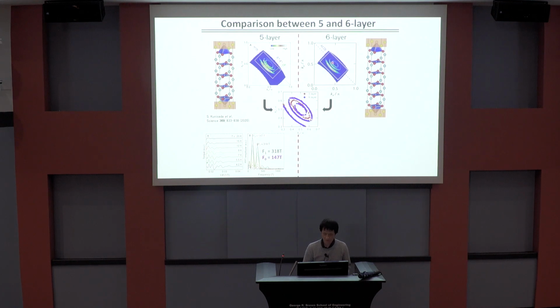And here I compare the pocket. This is the result I already showed, and this is a new result from the 6-layer. They look similar, filling arc and double pocket, but if you compare in detail, you can see a difference, but only in the smaller pocket—it looks much smaller in the 6-layer. This result was also confirmed by quantum oscillation.